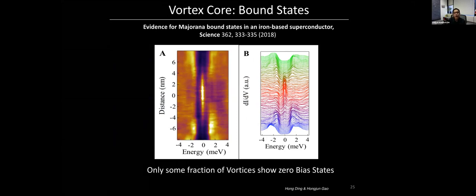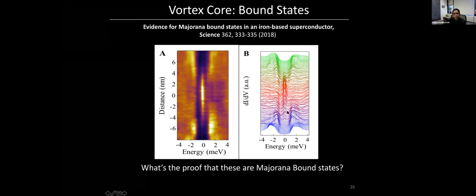Hong-Jun Gao. They did some really nice work showing for the first time that you see this zero bias vortex state in this material. The problem is that at the beginning, when this work was done around 2018, they found that only a small fraction of the vortices would show these zero bias states. So there was that problem.